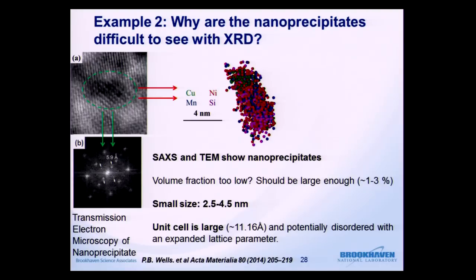Is it because there's just not enough of them? Well, according to our SAXS measurements, there's 1 to 3%, and that should be enough to see with high-resolution X-ray diffraction. But they are very, very small. They're 2.5 to 4.5 nanometers. And for these types of materials, they have a relatively large unit cell. The unit cell is 11 angstroms. So some of the precipitates might only be a couple of unit cells in size. And that means that there can be size effects. So those nice cubic structures and the crystal structure may be distorted just because of the small size. And that can occur strictly because of the size or also because of the interaction between the particles and the surrounding matrix.